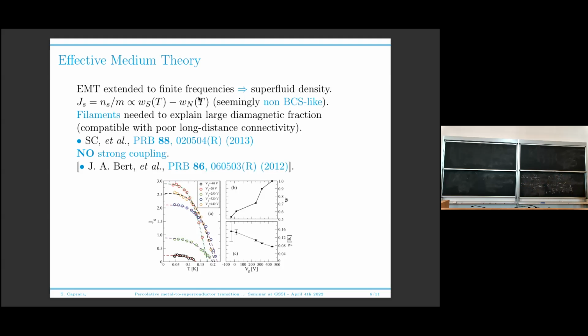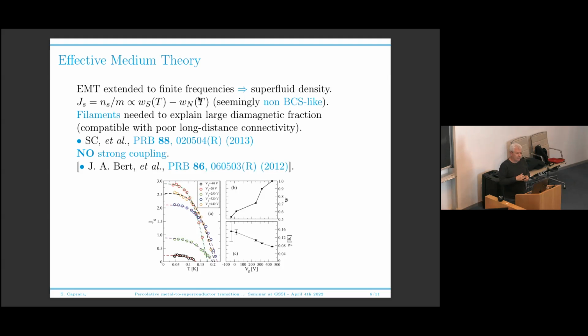This is just to show that with effective medium theory, you have a very reasonable description of your superfluid density. And this is something which is very different from the superfluid response of a standard homogeneous superconductor. Especially look, this curve here, you could never possibly describe this with a standard superfluid response of a homogeneous superconductor. This is a situation where your superconducting cluster is very close to percolation. So you have a very, very tiny advantage in the density of superconducting islands with respect to the metal. So they make a very, very small superfluid response.